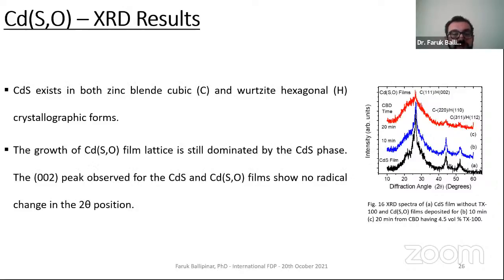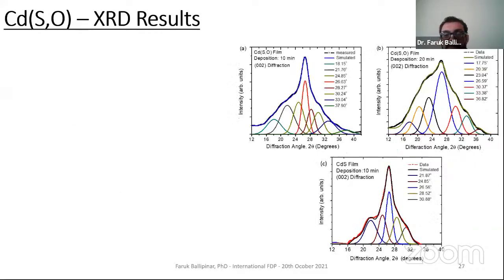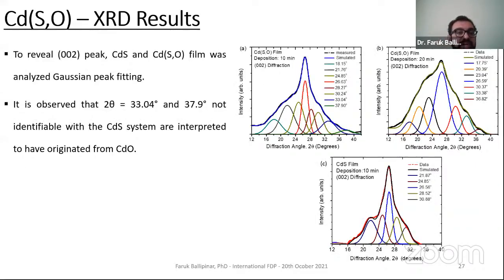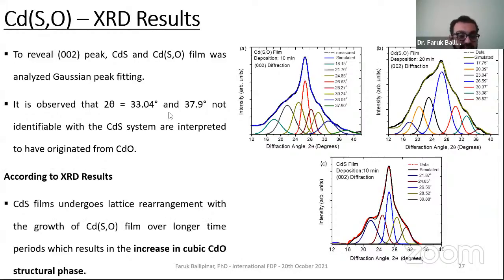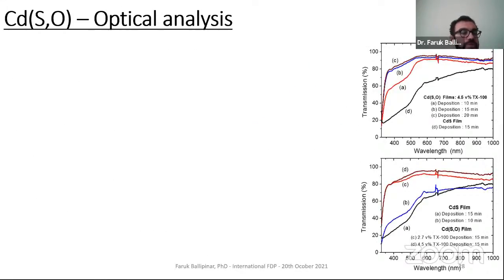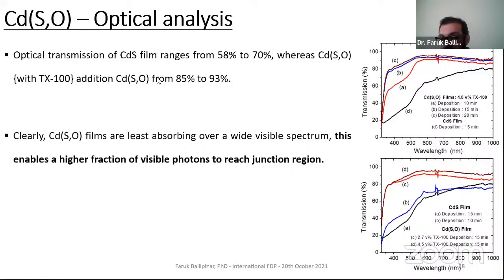Looking at the XRD results, there is no radical change in 2 theta position for these samples, but when analyzing with Gaussian peak fitting, we can get some extra peaks which originate from the cadmium oxide phase. So basically, XRD and Raman results match. We have cadmium oxide and cadmium sulfide in the phase. This is the critical part, the optical analysis. The black one is the common CdS, and the purple one is the CdSO film with a concentration of 4.5% TX100 surfactant.